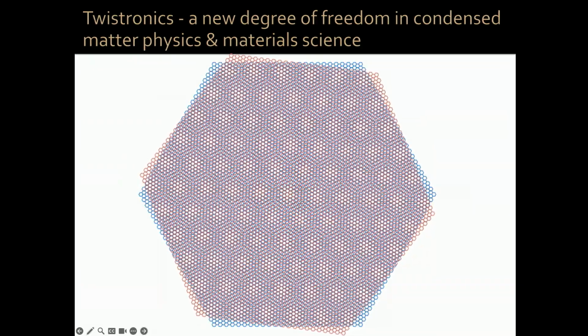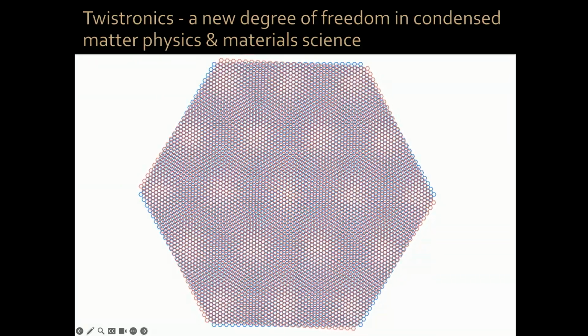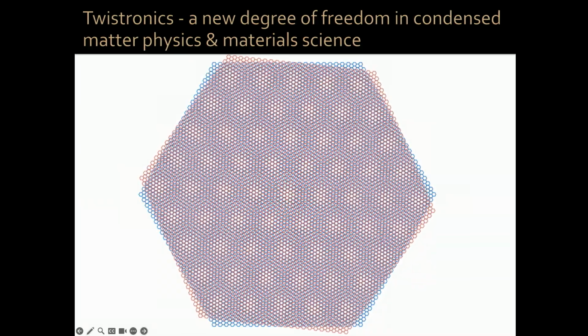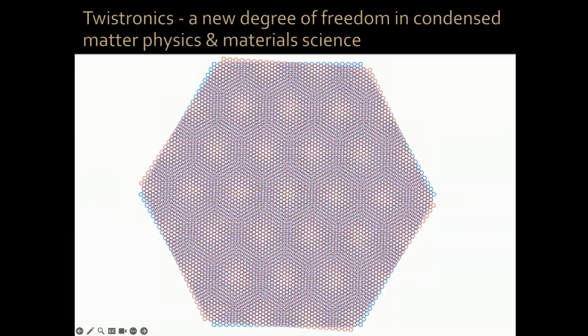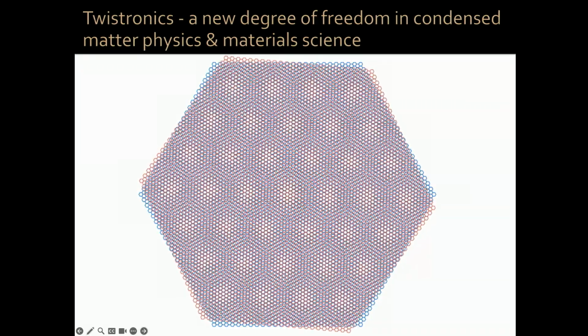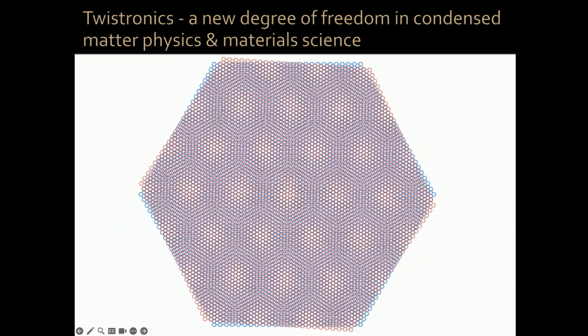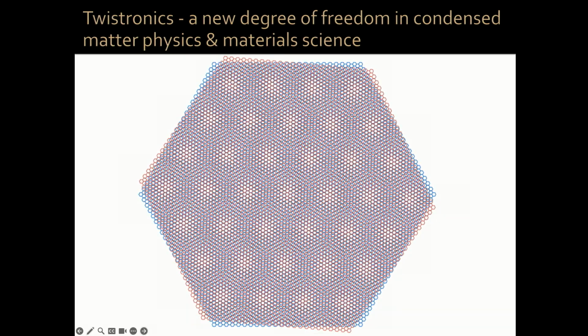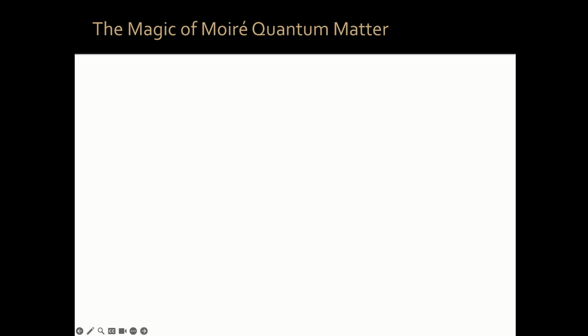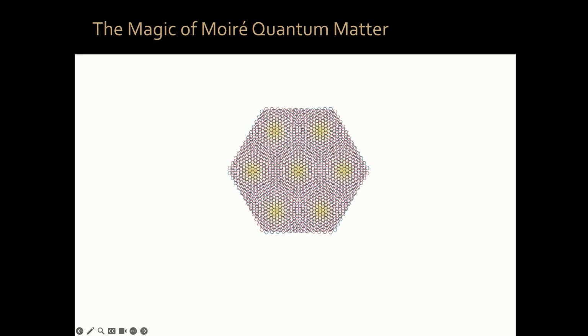And the amazing thing is that the electronic, optical, mechanical properties of the combined heterostructure can differ dramatically from the constituent layers. Yeah? So using this trick, which sometimes is known as twistronics, the community has been able to realize pretty much all of the phases of quantum matter that we know and discover quite a few new ones which didn't exist before. Yeah? It's called Moiré quantum matter because of the Moiré pattern that forms when you superimpose 2 periodic structures and rotate them one with respect to the other. You can also do the same trick without rotation if those 2 lattices are not identical. You also form a Moiré pattern.